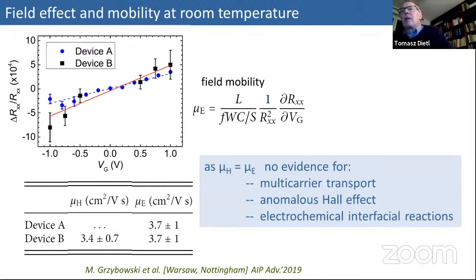Imagine that for some reason you have huge anomalous Hall effect in copper manganese arsenide, then you will have linear dependence on the magnetic field of it, because magnetization is linear in the magnetic field. And then your determination of Hall density will be wrong, because you will have a linear slope due to anomalous Hall effect and not due to normal Hall effect. So I wanted to say that this agreement between these two, you're assuming from the canting. Yeah. Because otherwise, it's not normal Hall effect expected, because you can have anomalous Hall effect in a collinear antiferromagnet, but not in this one, because this one crystallizes in a system where you have the lattice coupled by a translation operation, which necessarily gives you an effective time reversal symmetry, which kills anomalous Hall effect. But others you can. So I'm glad you don't observe it. Otherwise, it would be bad.